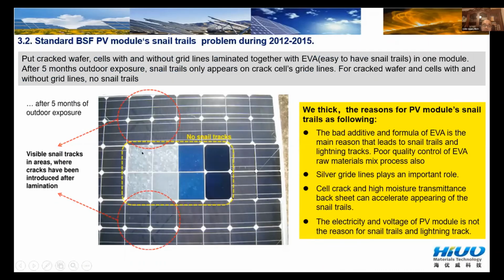So the most important is another test they did. They made a module with the wafer, with the cell, just without the grid lines on it. They laminated it together with some EVA sensitive to snail trails. They put that outside for 5 months of outdoor exposure. We find that only the area with the silver lines can have snail trails. Other places do not have. Here there are no silver lines. They do not have snail trails at all, okay?